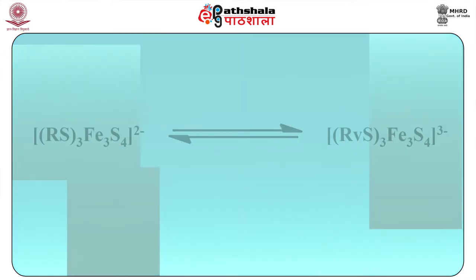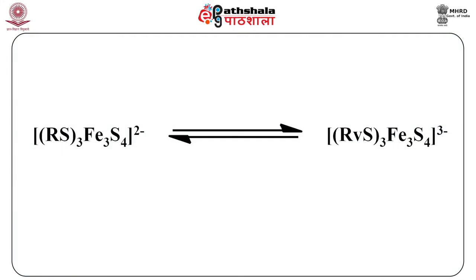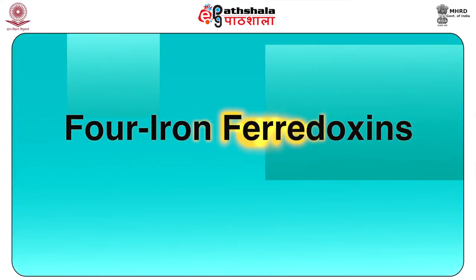In a number of iron sulfur proteins, the Fe4S4 clusters can be reversibly converted by the oxidation and loss of one iron ion to form Fe3S4 cluster. An example includes the inactive form of aconitase, which has an Fe3S4 and gets activated by the addition of Fe2+ and a reductant. In oxidized form, all the 3 iron atoms are as Fe3+, and in reduced state, it contains 2 Fe3+ and 1 Fe2+. Next ferredoxin we have is 4 iron ferredoxin, which is represented as 4 iron 4 sulfur.